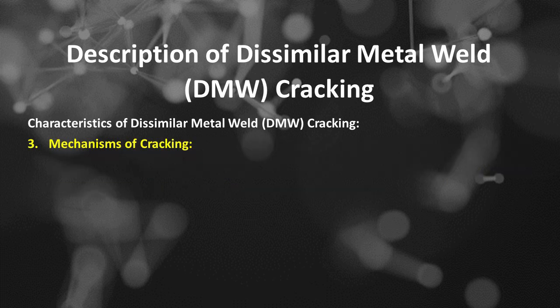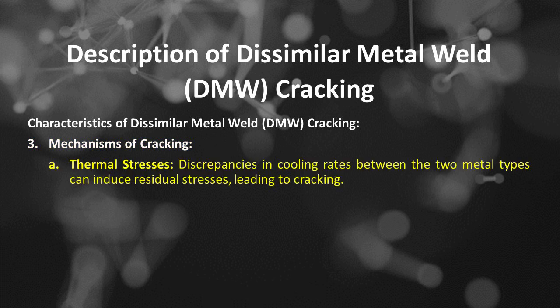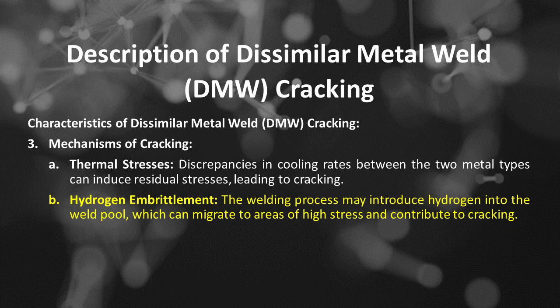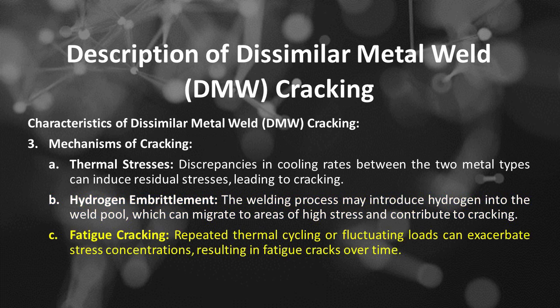Number 3 is mechanisms of cracking, such as following. The first is thermal stresses. Discrepancies in cooling rates between the two metal types can induce residual stresses, leading to cracking. The second is hydrogen embrittlement. The welding process may introduce hydrogen into the weld pool, which can migrate to areas of high stress and contribute to cracking. The third is fatigue cracking. Repeated thermal cycling or fluctuating loads can exacerbate stress concentrations, resulting in fatigue cracks over time.